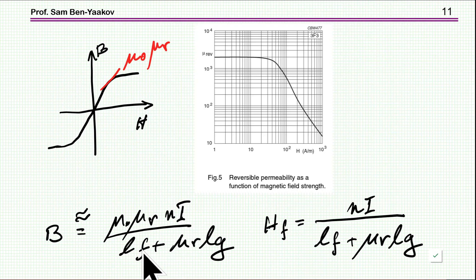So what we see here is that the magnetic flux density in this structure is a function of the permeability of the ferrite, this vacuum permeability, the constant n times i, and then we have the length of the ferrite and the length of the gap. Now if μᵣ is very high, very large, which it is because it's ferrite, it's about 2000. This is the μᵣ for ferrite 3F3, which is the local derivative of the BH curve at a given H.